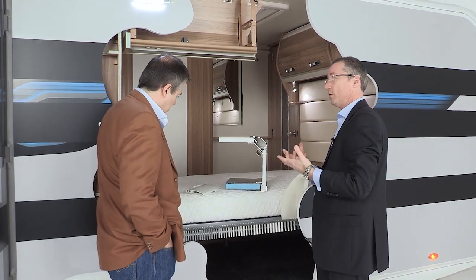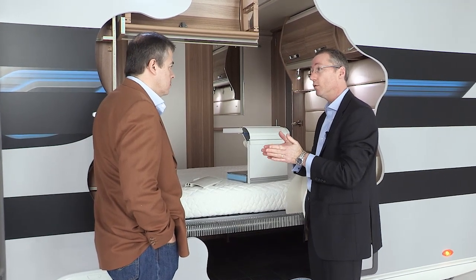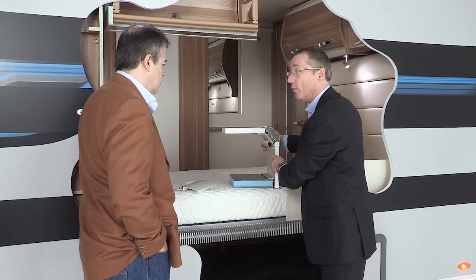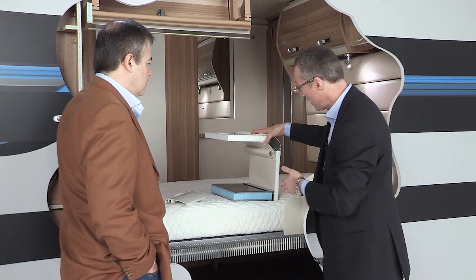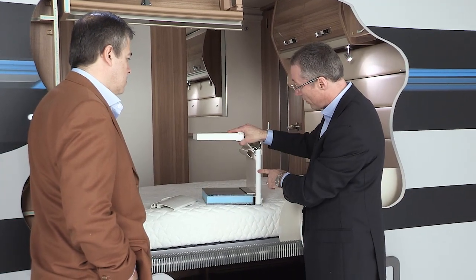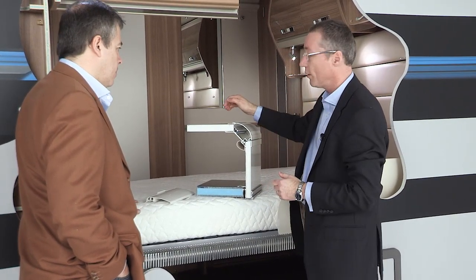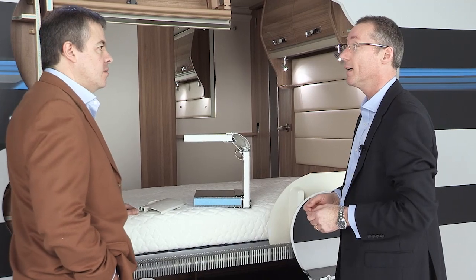The first decision was what material we were going to use for the walls. We decided to use a very strong and robust GRP surface for the exterior. But we wanted a balanced panel to make sure there weren't any thermal expansion differences between the outside and the inside walls. So it meant we had to have GRP on the inside of the caravan as well. We worked extensively with a supplier to laminate decorative paper onto GRP for the interior surface, achieving a balanced panel sandwiched in the centre with polystyrene. That resultant panel is very strong, tough, and readily decorated — so you don't need to worry about doing anything else.